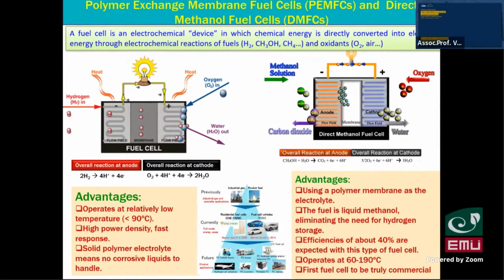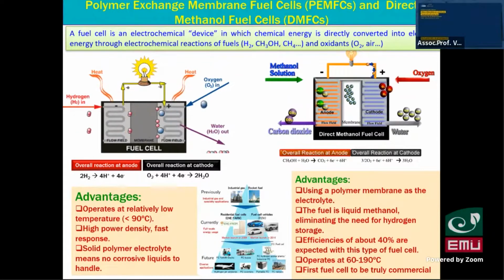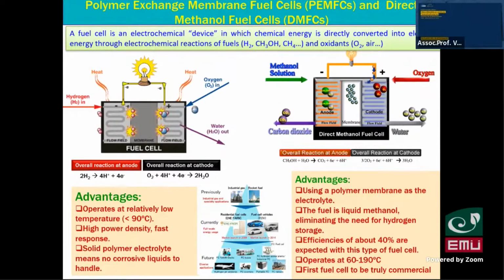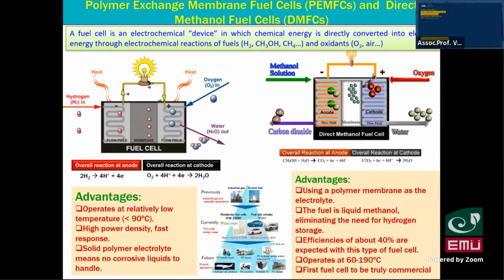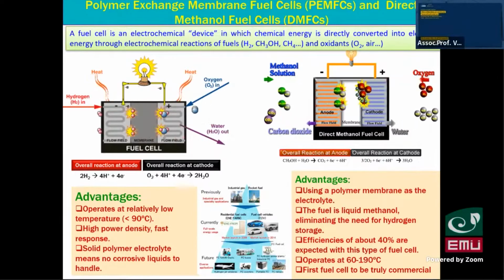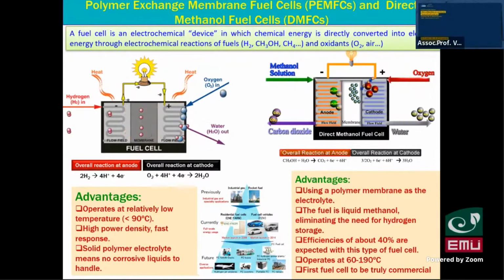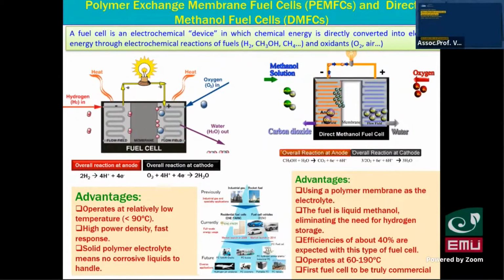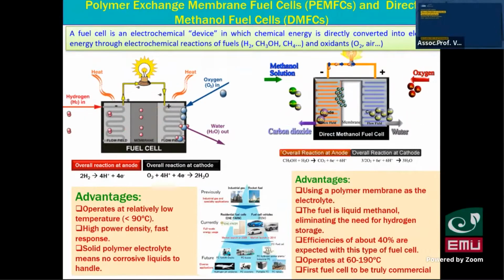The operating temperature is also low, around 60 to 190 degrees C. In my experience, I operate around below 100 degrees C. This was also the first fuel cell to be fully commercialized.